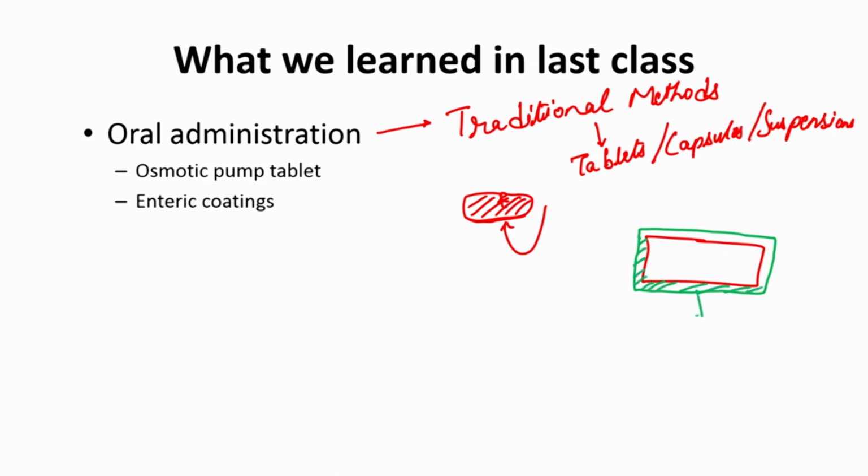These polymers are nothing but polymers composed of polycarboxyls, and because of that they have some pH responsiveness, where at low pH these will be protonated and will have low solubility, but at higher pH these will become ionic and have very high solubility, it will dissolve away, and only then the drug will get released out. That way you can protect the drug from harsh environment.